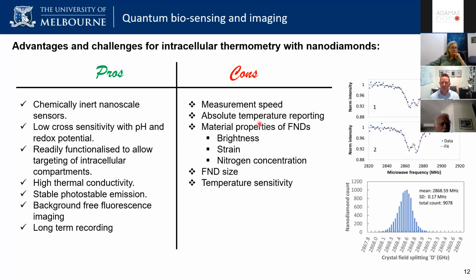Some of the real challenges are to do with the measurement speed, I think. So often in these sorts of systems, you want to track these nanodiamonds in real time and be reporting the temperature very quickly, rather than relying on averaging over multiple points. So I think measurement speed is one thing, and that's linked to the particle brightness, if you like. The other thing is that the nanodiamond systems don't report the direct temperature. So we can monitor temperature changes if we're able to follow the same nanodiamond, but we don't have a direct measurement of the temperature itself. So this often relies on an external calibration.